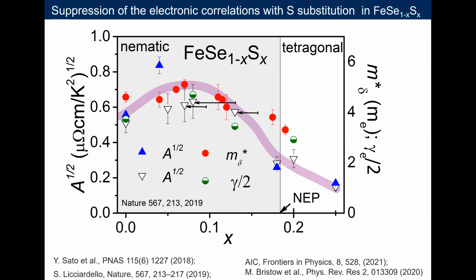These are the data probing the changes in the effective masses for the largest pocket we see in quantum oscillation, which is the outer hole pocket, the delta band. What it shows us is that the effective masses do not have divergent behavior in the vicinity of the nematic endpoint. Instead, all the collated data from specific heat and from the A coefficient point to a behavior represented by this colored curve: there is a small enhancement inside the nematic phase, and then the behavior decreases away from it. And what about the mass enhancement of the other pockets?